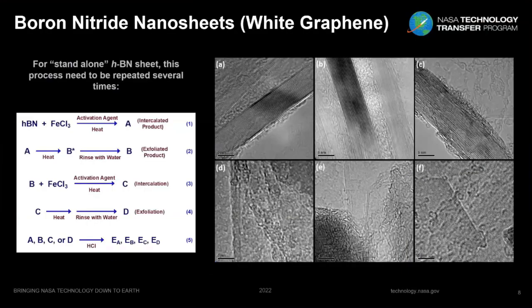If you want to produce a standalone hBN, what we call here the boron nitride nanosheets or the white graphene, you can repeat the same procedure that we just discussed as many times as you want to decrease the thickness of the layers until you obtain your desired layers. Here I'm showing in the TEM micrographs layers that go from 2, 4, 6, 8, all the way to 20 layers, and it is pretty cool to see that you can get all the way to 2 layers of boron nitride with this process.